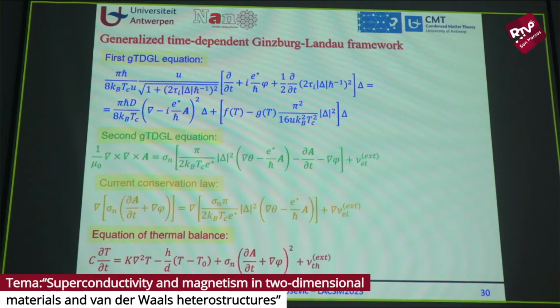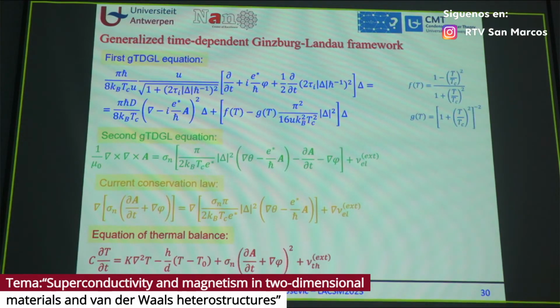I just want to show you the methodology that we need to model the behavior of a superconducting device made of 2D materials or otherwise. It's the time-dependent Ginzburg-Landau framework. This is the core of this code that I mentioned. We have the first Ginzburg-Landau equation that describes the superconducting order parameter that is connected to the density of our carriers of superconductivity. This is also where the temperature dependencies come into play, and we are not using the standard Ginzburg-Landau temperature dependence, but the modified one that has been proven to model experiment better at lower temperatures away from Tc.